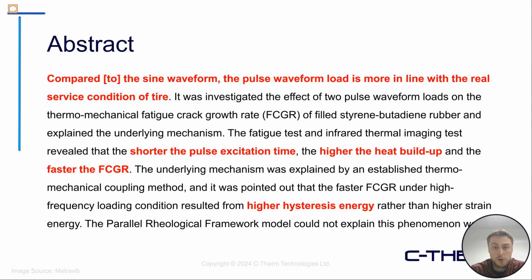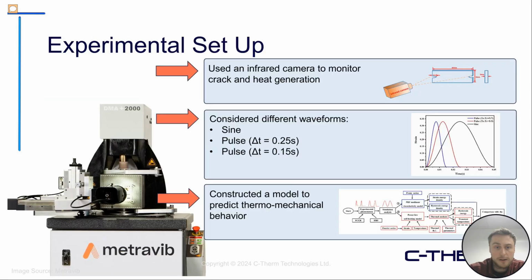And what the group found was the shorter pulse excitation time generated more heat buildup and had a faster crack growth rate. They related this to the higher hysteresis energy. So we'll look into that here.